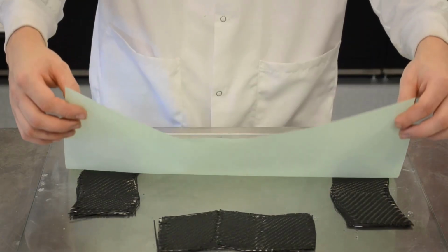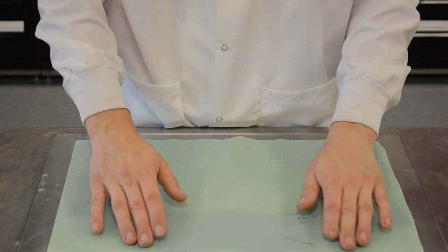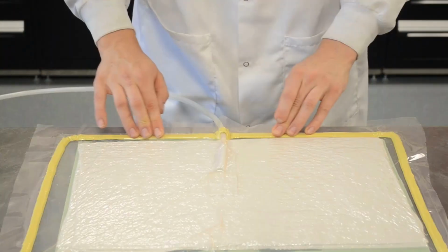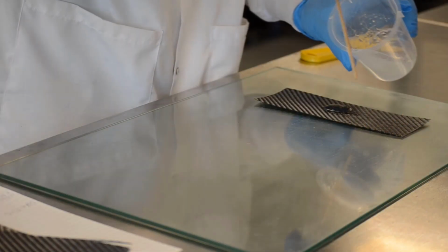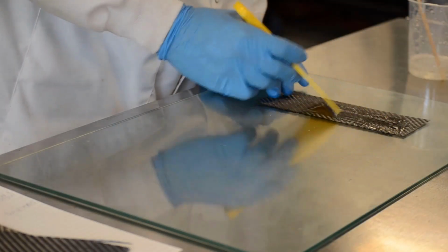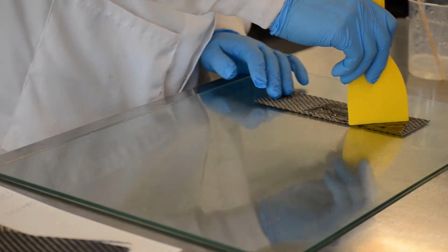A potential explanation for this is that entrapped air in the vacuum-bagged samples will expand to a larger volume in between the fibers and displace some resin into the vacuum consumables, whereas entrapped air in the non-vacuumed part will remain at the smaller volume that it occupies at atmospheric pressure.